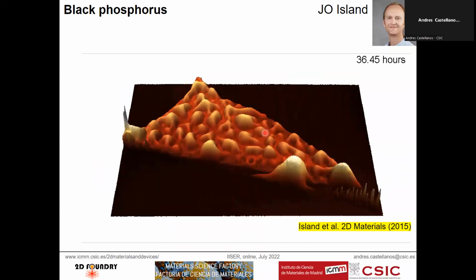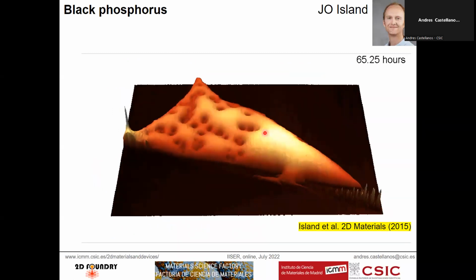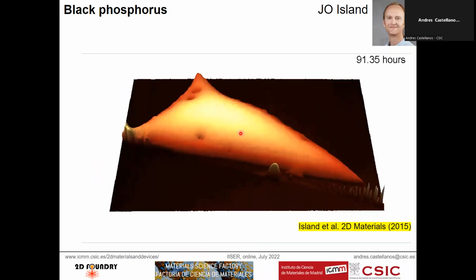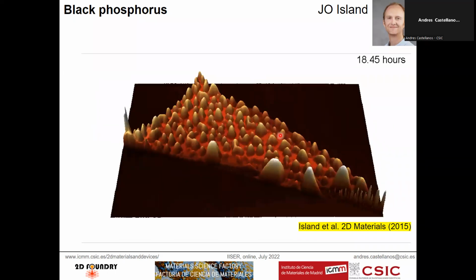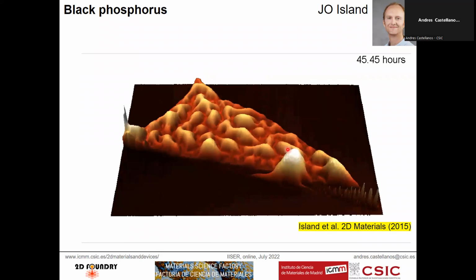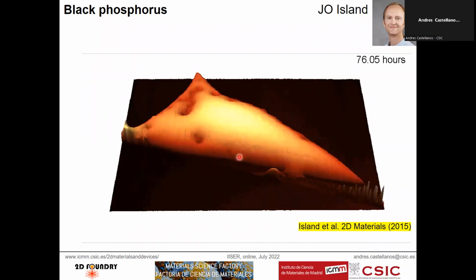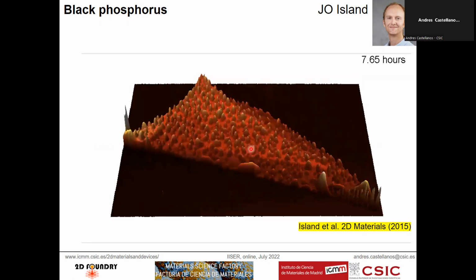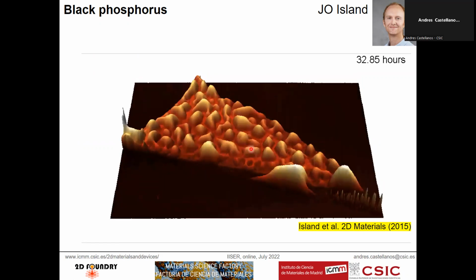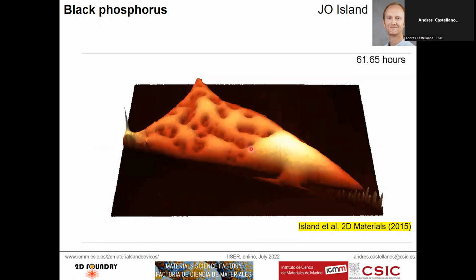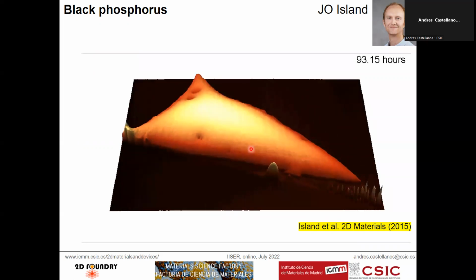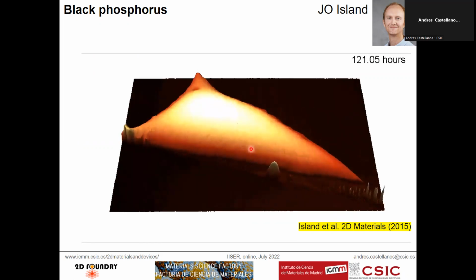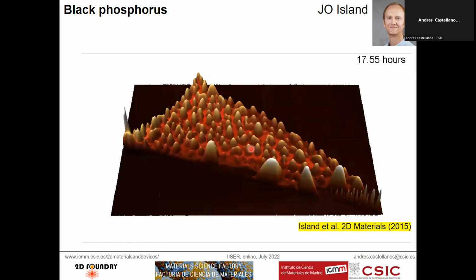A disadvantage of black phosphorus is that it's very temperamental regarding environmental exposure. If you expose black phosphorus to air, it's highly hygroscopic, and the reaction with the oxygen and dissolved water tends to degrade it. So you need to work out different ways to encapsulate it or to work in vacuum all the time and so on, right? So this is basically the drawback of black phosphorus.